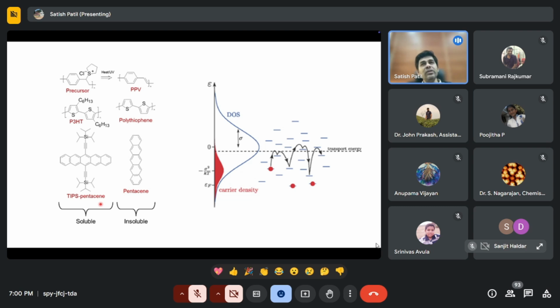But it has its own downside of introducing this alkyl chain. As I mentioned, these alkyl chains do not participate in transport mechanisms. So that's the reason one has to be very careful about the length of these alkyl chains. These alkyl chains should not be very, very long. Then they introduce defects in the structures, because the interspacing between the polymer chains becomes larger and larger. For the charges to hop from one chain to the other chain, you need an increase in activation energy, and then sometimes the charges get very localized, and then you have defects in the structures. Each blue line here shows the charges hopping from one place to the other place. So you require very high activation energy for the charges if you have a very long alkyl chain.